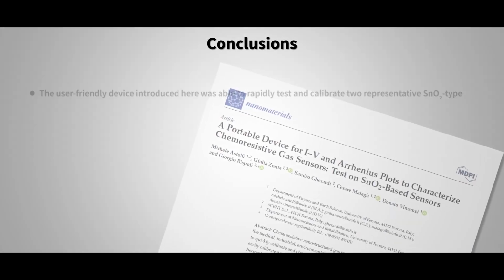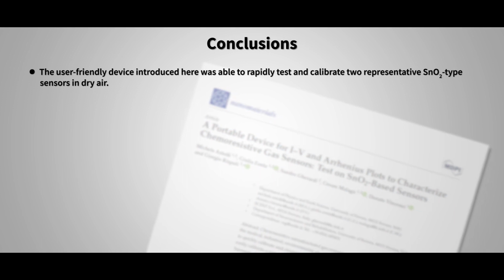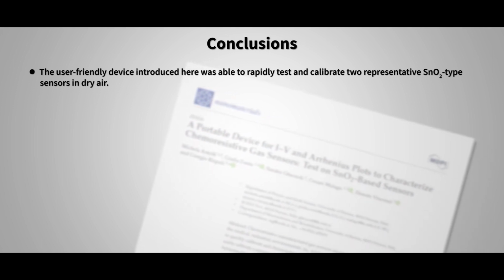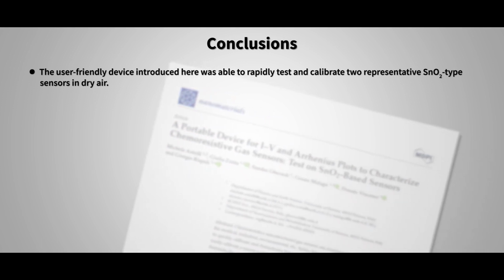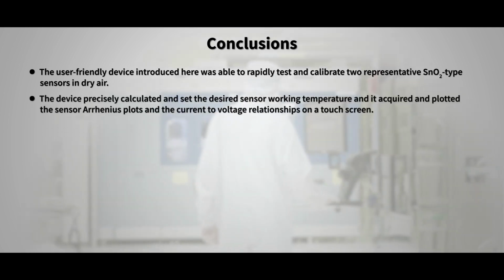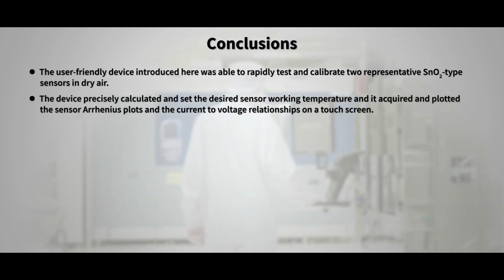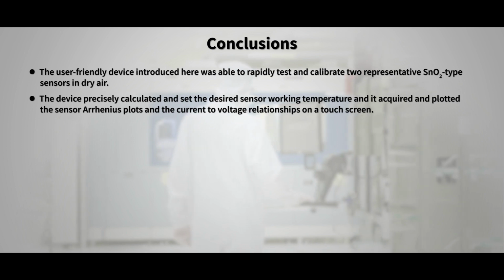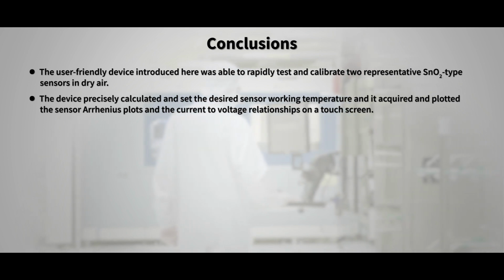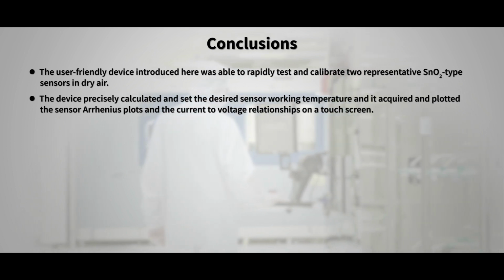Conclusions. The user-friendly device introduced here was able to rapidly test and calibrate two representative tin oxide type sensors in dry air. The device precisely calculated and set the desired sensor working temperature, and it acquired and plotted the sensor Arrhenius plots and the current-to-voltage relationships on a touch screen.